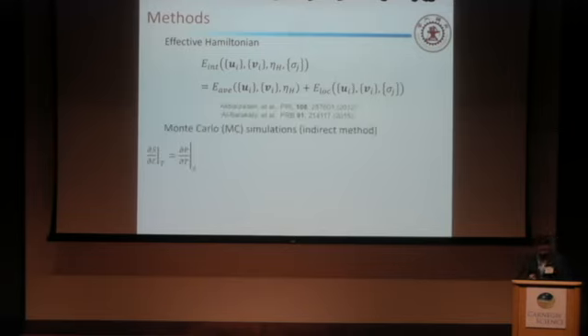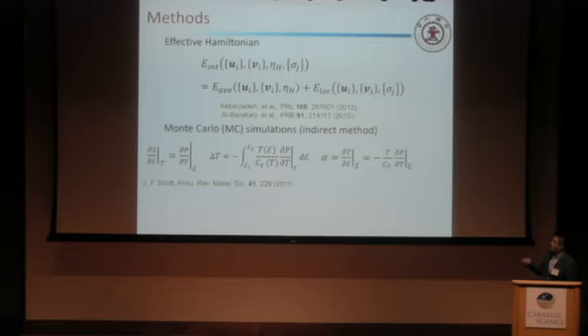So the first method we introduce is the indirect method. This indirect method is based on Monte Carlo simulations. Also, it's based on the Maxwell thermodynamic relations. From this, we can get the delta T change and the alpha. The alpha represents the electrocaloric coefficient. Here, we call this method MC1.